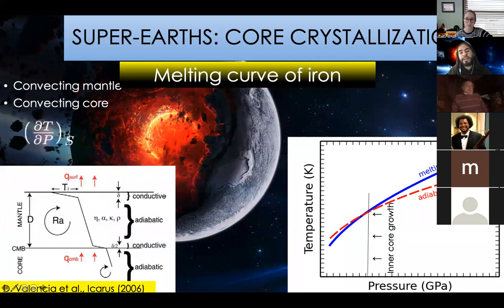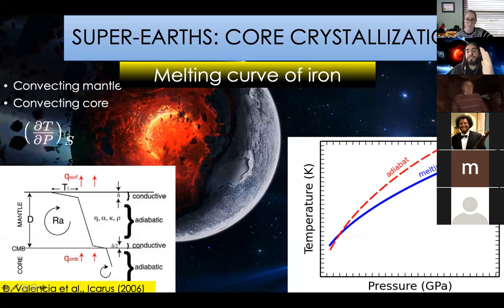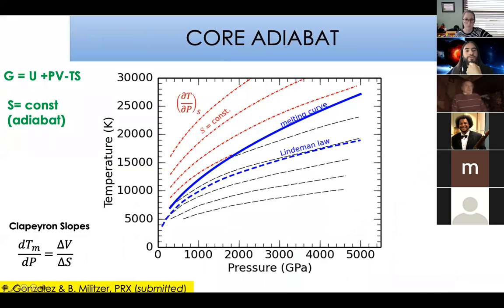So if an adiabat in the pressure temperature diagram looks like this and intersects the melting line with a shallower slope, it will mean that the core of the planet will start growing from the center. But if the adiabat has a higher slope, then it means that the crystallization of the core will start from top to bottom. So that already will tell us about a formation scenario. And that is what we did with iron.